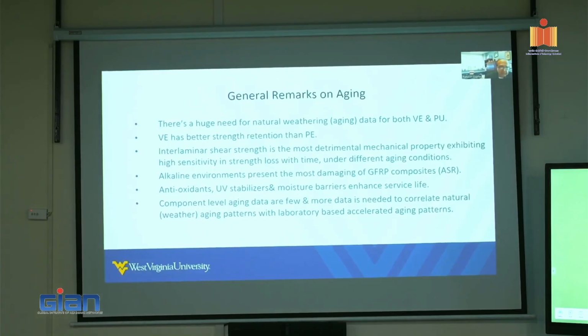It is found that vinyl ester has better strength retention than polyester, and it is found that the mode of deformation that is very useful to examine is interlaminar shear strength, because this depends on the properties of both the matrix and the reinforcement. It is found that alkaline environments present a very damaging atmosphere, but this can be countered by the use of antioxidants, UV stabilizers, and moisture barriers. So we obtain component data in the lab, and we correlate that with field data using equations which have been proposed